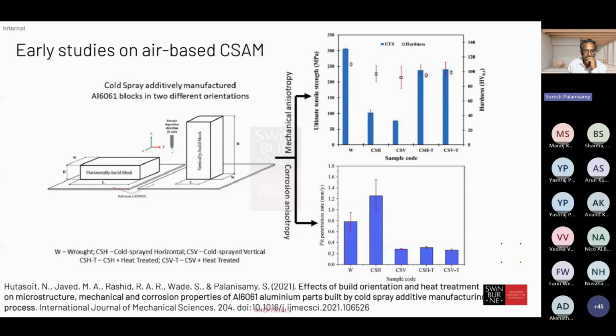Sure, thanks. These are some of the early studies which we did. Most of the work was done in aluminum 6061 material, aluminum 6000 series I would say. So horizontal build, again vertical build. It's good to see that quite different properties are achieved in the different conditions. And also heat treated condition, this is the wrought properties compared to the heat treated properties. As you can see, in the as-built condition you're not achieving significant tensile strength. But once it's heat treated, you can see the significant variation in the tensile strength and also the other properties.